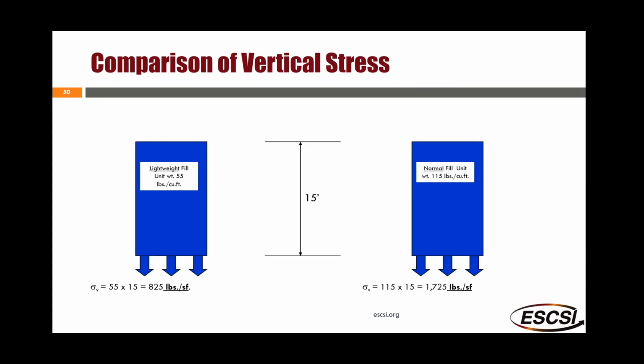The same is true for applied vertical stress. You reduce the weight, you reduce the applied vertical stress. In this example, comparing a 55 PCF lightweight aggregate fill to a normal fill, you end up with less than half of the applied vertical pressure, which can be significant if there's a bearing capacity issue.